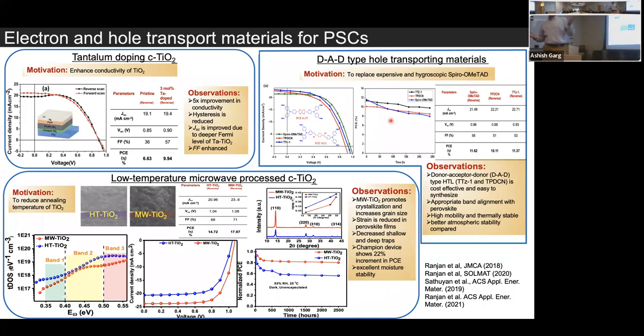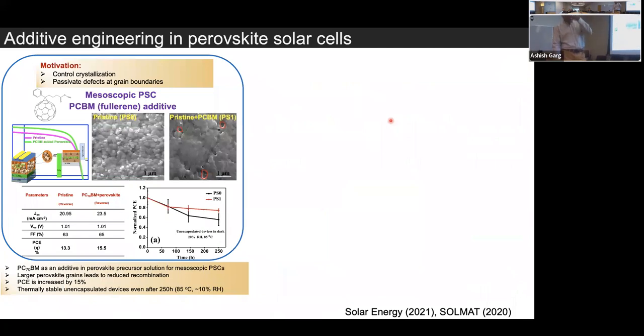Another thing that we have done is to look at hole transporting materials which can replace spiro. We have looked at alternate hole transport materials to replace spiro-OMeTAD, and we find they're not very high performing, but they can give you efficiencies between 10 to 15% based on these donor-acceptor-donor configurations of organic materials. These are also synthesized. The problem with spiro is it takes a long time to process, it's very degradable, and it's expensive. These materials are cheap, they can be made easily in the laboratory, and they are low temperature materials.